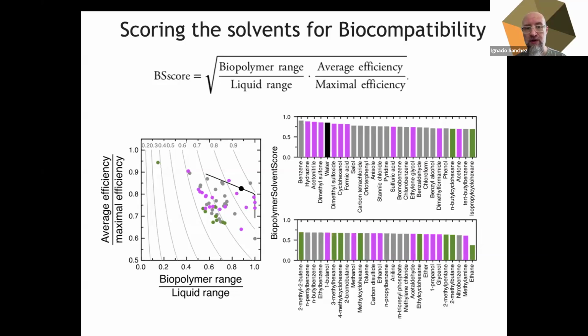Are they all the same? No, they are not. The ranking of the biopolymer solvent score is to the right. You see that there's a wide range of scores from approximately 0.9 to approximately 0.4, and that water is close to the top. So all solvents we consider can lead to biopolymer folding and evolution, but water seems to be particularly good.